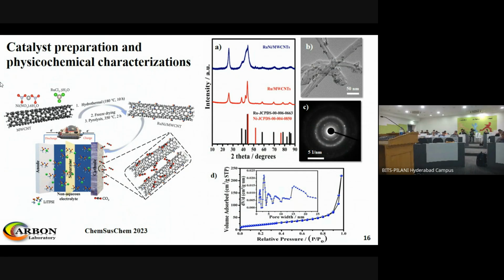These are just typical characterization techniques, XRD, TEM and HRTEM, to ensure that we have the ruthenium nickel multi-wall CNTs. So you can see how the ruthenium nickel bimetallic catalyst is nicely dispersed on the multi-wall CNT.